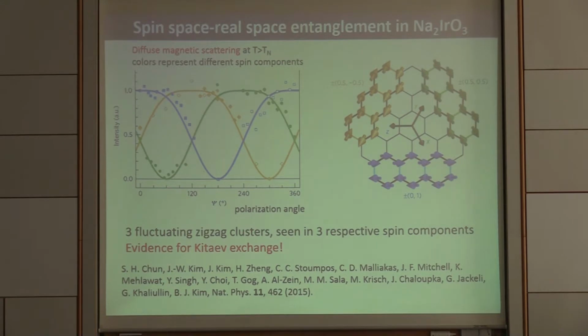That arises when looking at the diffuse magnetic scattering slightly above TN with magnetic resonant X-ray scattering. Here it was found that all three different possible zigzag domains are formed as short-lived and short-range clusters above TN, but they are seen only in different spin components. So polarization-dependent X-ray scattering revealed a clear coupling between the direction of the ordering wave vector and the spin component of the moment. So there is really this entanglement between spin and real space, which is characteristic for the Kitaev-type model, and that proves that the Kitaev-type exchange is very important in this material.